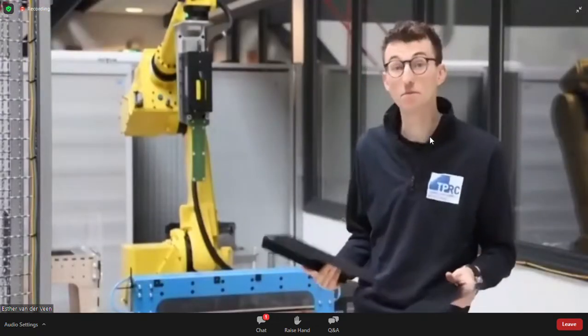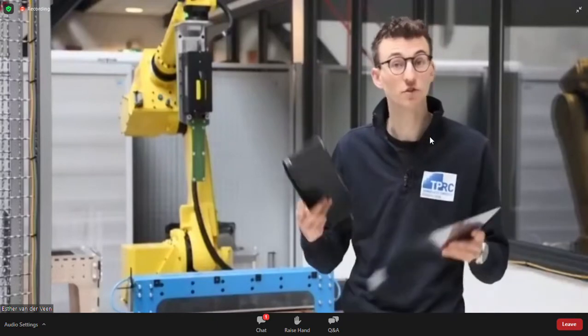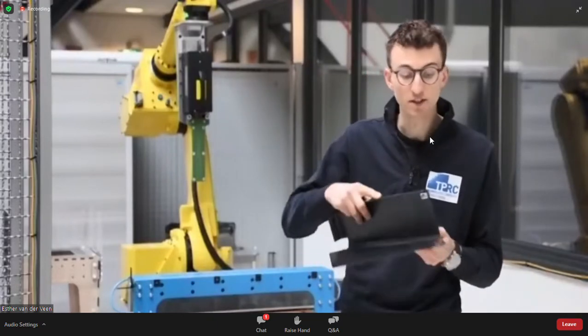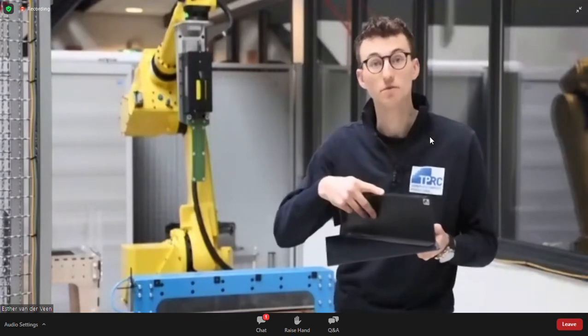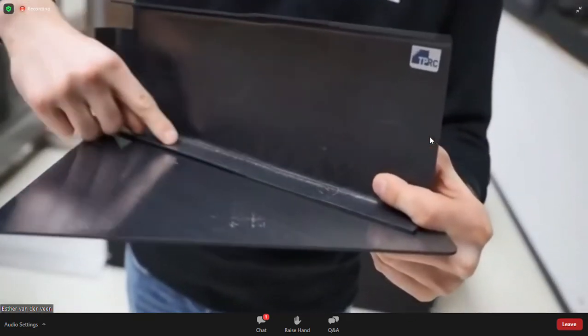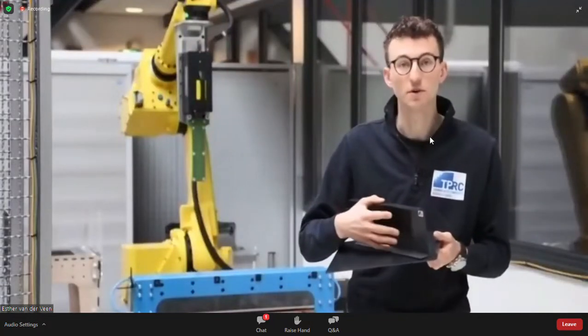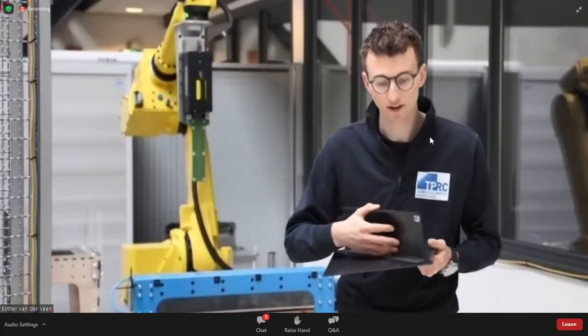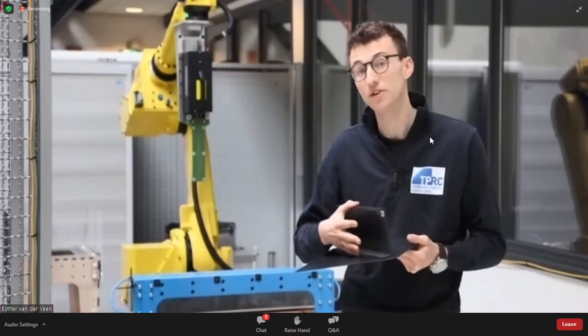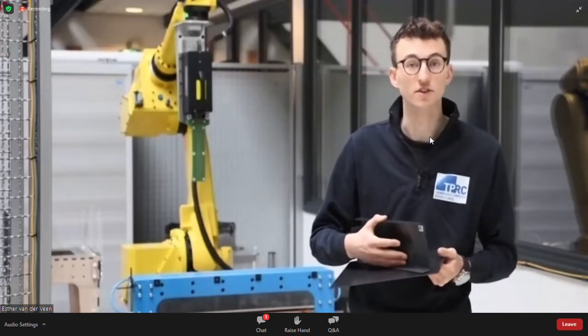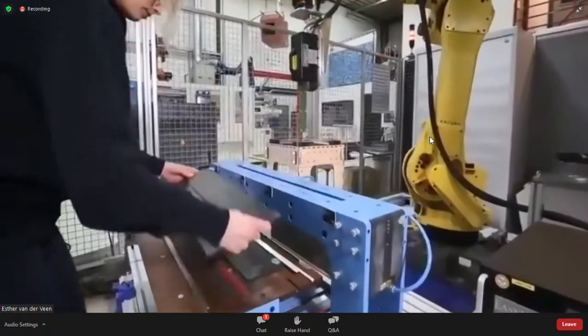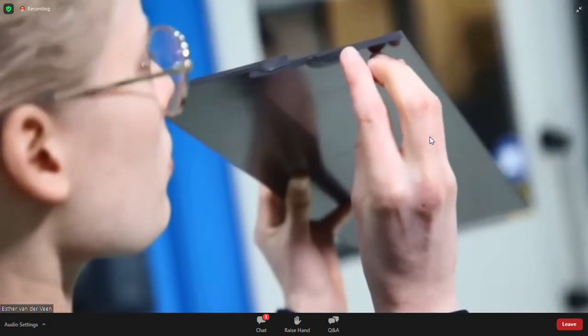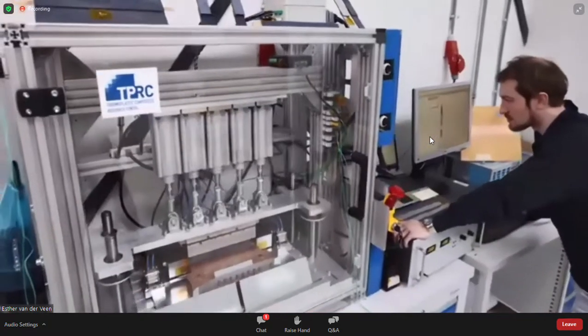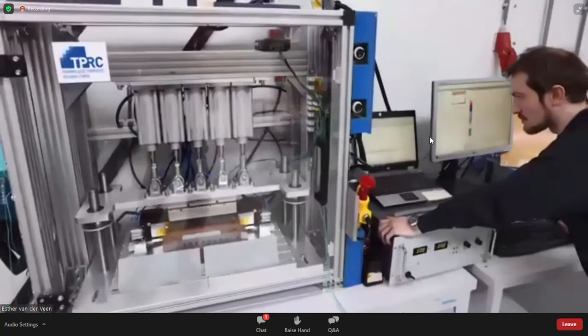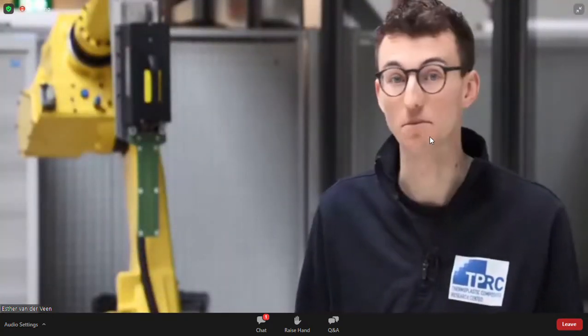So now with welding, we apply the same principle of fusion bonding by taking 2 finalized components, fixing them in a mold together and applying the time, pressure and temperature now locally to melt the interface of the 2 parts while they will consolidate into one singular structure in the end. Applying this temperature and pressure locally, therein lies the challenge, and that's the key difference here. Now, different welding technologies exist for thermoplastic composites, and they mainly vary in how this local temperature is applied to the joint interface. Takeaway, however, is that welding by fusion bonding is simply very natural to the manufacturing process of thermoplastic composites.